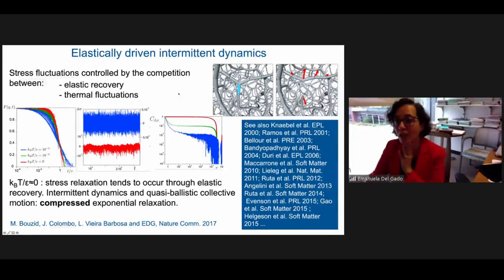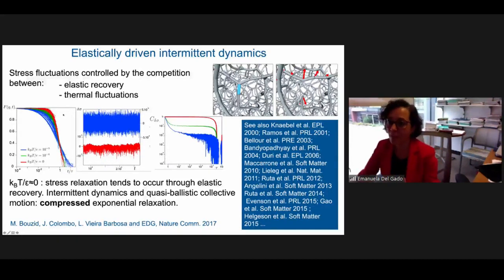So basically, we've done a simulation of a three-dimensional model of one of these gels, where we were breaking part of the structure to watch how these processes would induce stress fluctuations in the system. And we were watching the relaxation processes that would be the consequences of these events, as would happen during aging of the material, due to the presence of small thermal fluctuations or to the relaxation of internal stresses that are built in during the solidification. What you can see is that, because the thermal fluctuations can be very, very small, most of these fluctuations are driven really by the elasticity. And because they're driven by the elasticity, they are strongly correlated in space and time, which leads to very intermittent dynamics. The result is that the microscopic dynamics that we see results in compressed exponential, faster than exponential type of relaxation processes.